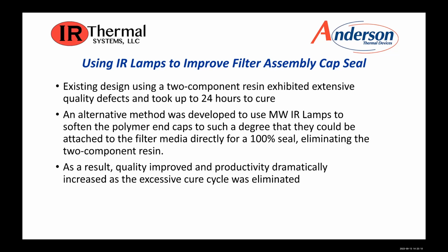It's a 100% seal. The two-component resins at times had gaps. It wasn't quite as uniform as they'd like, and this really helped them both in quality, dramatically improved productivity, and resulted in a lower cost of goods, and as I said, improved quality. So that's another very good example where infrared really can make a big difference.